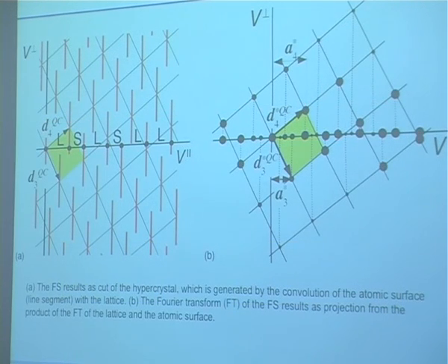And here you have the higher dimensional embedding. Again, that's a diffraction pattern which is one-dimensional in physical space and which can be seen as a projection of a two-dimensional lattice which is periodic. The slope of this lattice has something to do with tau. If you have a projection in Fourier space, then you have a cut in direct space. By Fourier transform, projection is related to a cut, and therefore you have here in direct space, in structure space, a lattice which is decorated by these line segments, and the physical space cuts the Fibonacci sequence out. So that's the secret between high dimensional embedding and quasi-periodic structures.